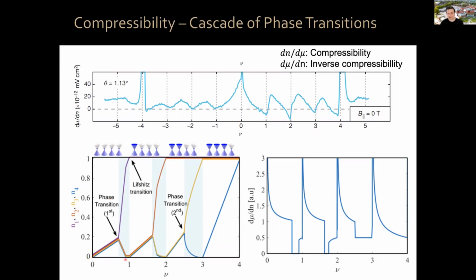But for example, when you are close to filling factor 1, so 1 electron per Moire unit cell, so when you're close to 1/4 filling of each of these flavors, the system decides to spontaneously fill 1 flavor completely and empty all other 3. Then the story repeats. You fill in the other 3 flavors, and at some point the system decides to fill 2 flavors, empty the other 2, etc. In a simple model, this gives rise to this sawtooth behavior. This is a very simple model. There are plenty of things one needs to go from this to the actual experimental data, and there are many interesting things like negative compressibility, etc. But this is just to give you a flavor of what happens here. There's a series of phase transitions at each integer.